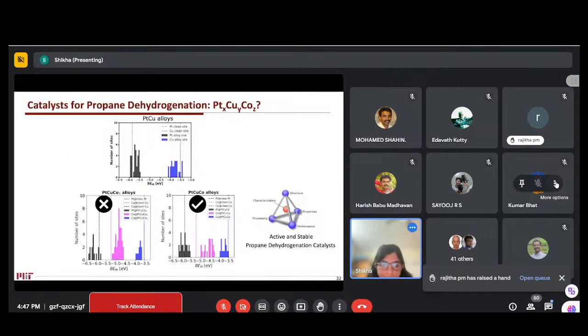Now, from our model, we want to give answers to our experimental colleagues. Here, when we do the mixing of platinum and copper, this vertical bar is the clean platinum site, and this is the copper binding energy on the clean surface. The binding energy shifting up means a higher binding energy, meaning the site is more active, and the copper sites are more stable. So adding copper gives some stability to the alloy, and also gives higher activity to the platinum site.